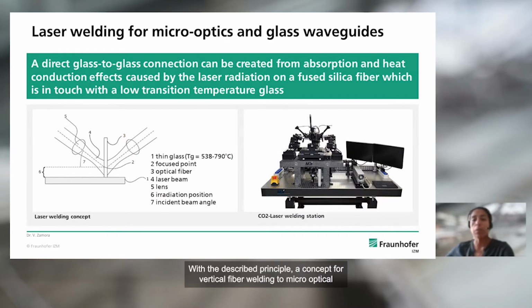With the described principle, a concept for vertical fiber welding to micro-optical elements with low temperature transition coefficients is proposed. Two laser beams are laterally focused on the fused zone by employing optical elements like lenses. Focus height, incident beam angle, and laser beam diameter have to be adjusted according to the material properties of the two optical elements and the resulting working point. In addition, the time of the laser power during the welding process has to be optimized.